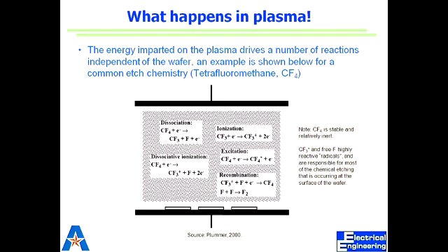I'll explain that. Right here, I wanted to show that this part shows the recombination process. When pressure is increased, the number of agents increases so much that they start colliding with each other. Due to high collision between the agents, they start recombining. Due to recombination, we lose most of the agents, so the etch rate starts decreasing. That's what I wanted to tell you.